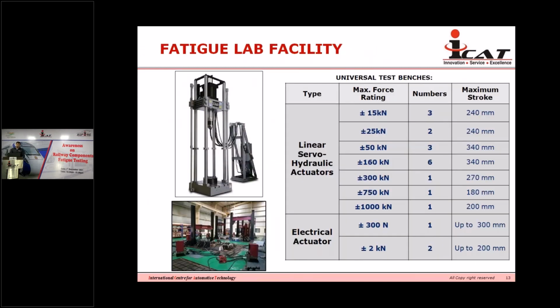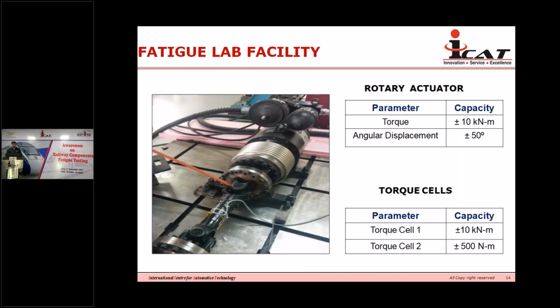using this facility. We have n numbers of actuators, like 17 actuators ranging from 15 kilonewton to 1000 kilonewton, and these are all servo hydraulic actuators, and we can go up to a frequency of 15 to 20 hertz, and we have a 1000 kN machine, we can go up to 50 to 60 hertz, and respective strokes. Also, we conduct propeller shaft testing and other shaft testing, like anti-roll bar torsional testing, using our rotary actuator. So we have a 10 kilonewton rotary actuator for testing of the coupler or torsional testings.